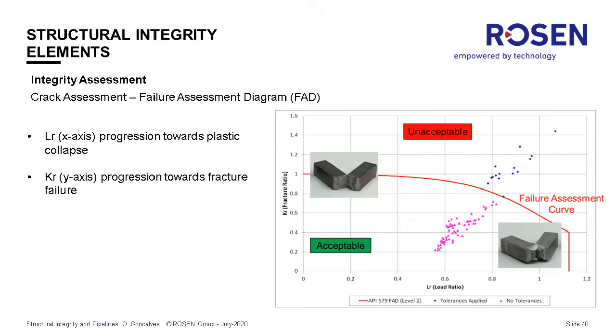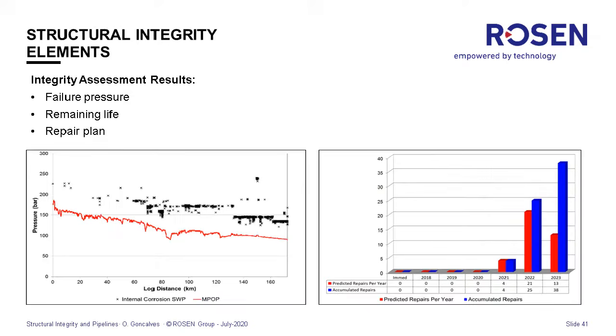And then for crack assessment, we use the methodologies that are based on a fracture mechanics approach, like the failure assessment diagram that is incorporated as a procedure in both API 579 and also BS 7910. And this would be basically the end result of integrity assessment. So in the chart on the left, you can see the black dots.